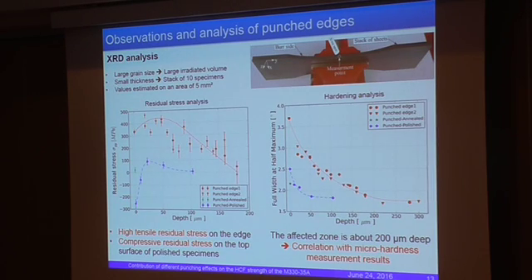So we use X-ray diffraction analysis. Just a word, as I mentioned, we have pretty large grain size, so we need to use a quite large spot size for our measurements. But since our sheets are very thin, we need to use a stack of 10 specimens, and so the results I am giving are averaged on the spot size, looking at 8 or 9 specimens.